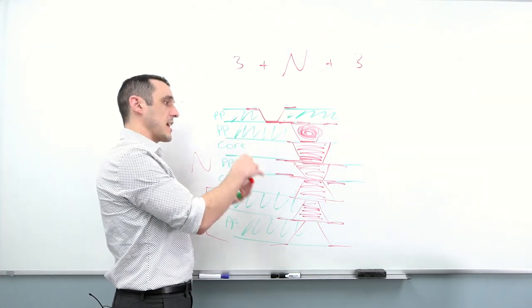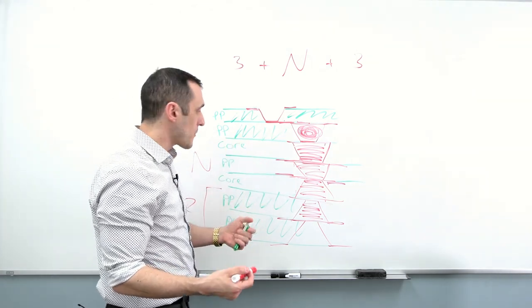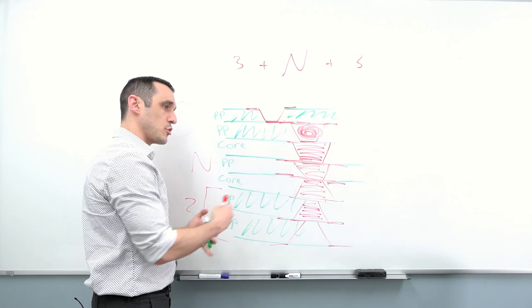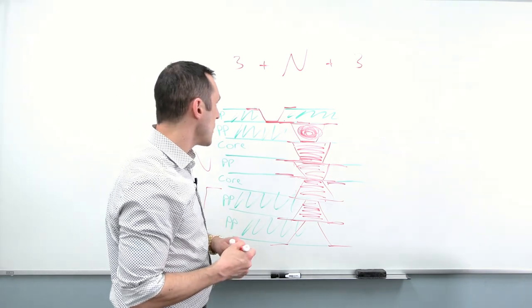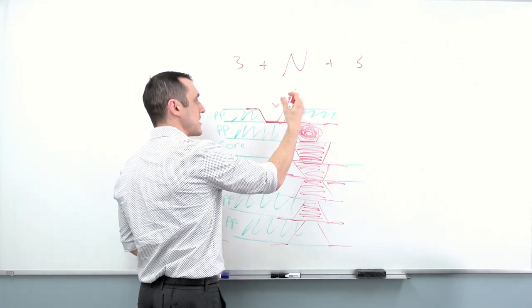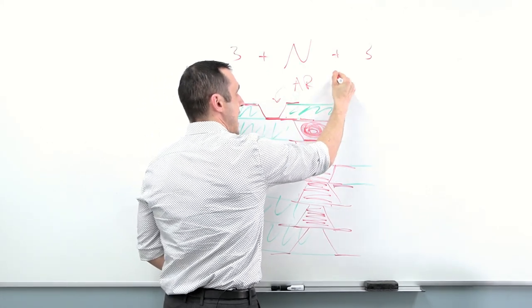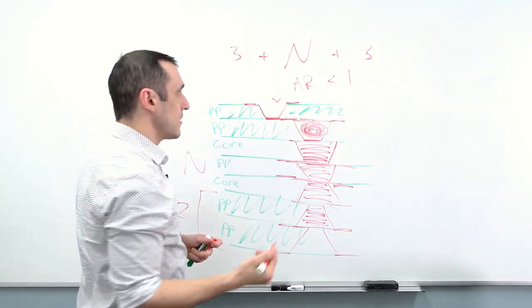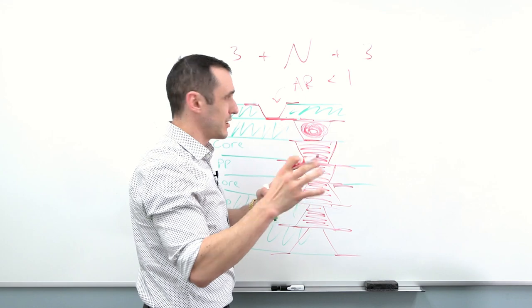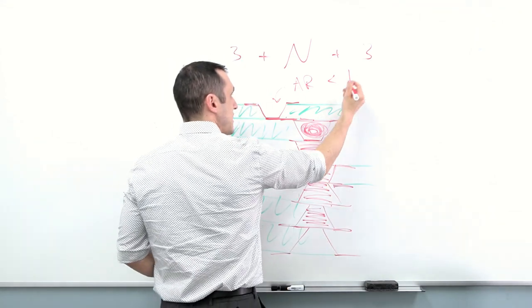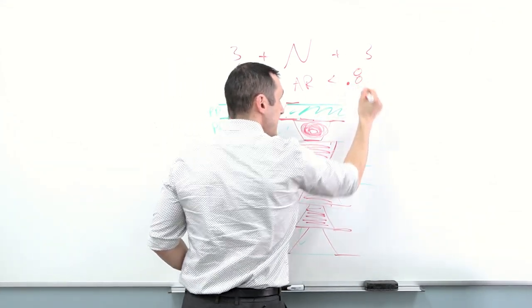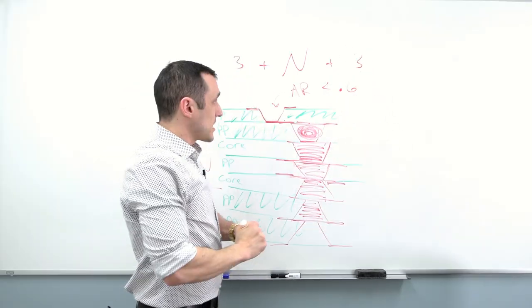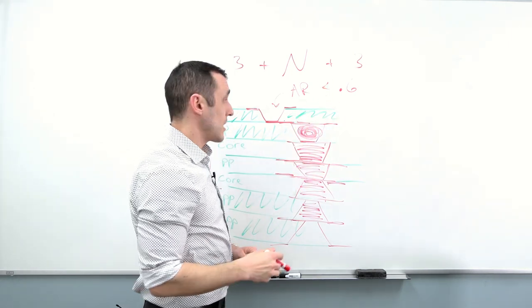Now, this is another point where reliability matters. If these aspect ratios are not correct, they're going to be at greater danger of failing. Essentially, if they're too large, they're going to be in danger of failing. In general, you would like to keep this microvia aspect ratio at less than one. You'll see different recommendations from different people. Less than one is kind of a good loose upper limit. I've seen this go down to less than 0.8, and then I've seen it go down as far as less than 0.6.